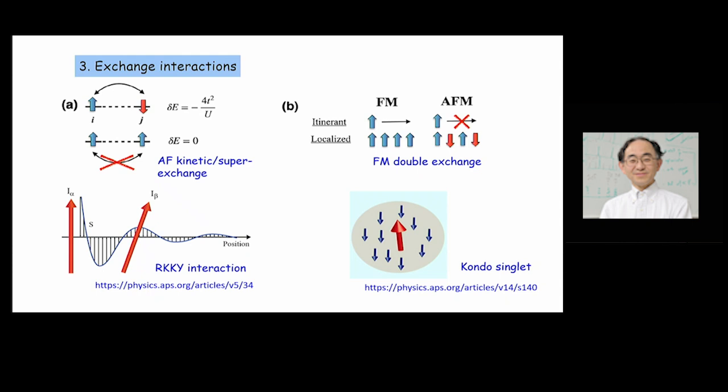So then once you dope, right? Originally you have an antiferromagnetic interaction, but you have doped carriers. So then ferromagnetic interaction is preferred. So there should occur the competition between the two cases, right? And once you have metallic conduction electrons and a localized spin, this is a different picture from this side. But now in this case, this localized spin will polarize the conduction electron spins.